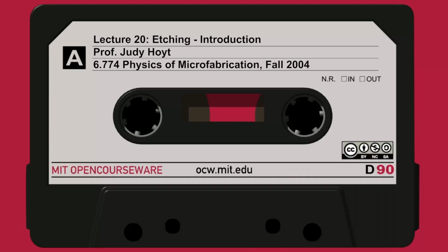So now, again, we express the over etch as a percent in time. So that's just going to be the worst case etch time, which we just calculated, divided by the nominal etch time. The nominal etch time would be the time to remove half micron at the nominal etch rate. So the nominal etch time is given by 0.5 divided by R_ox. So we just take the ratio of the worst case etch, the longest etch, to the nominal etch, and we get a 1.1. So that's about a 10% over etch, which isn't bad. To do a 10% over etch these days is pretty darn good.